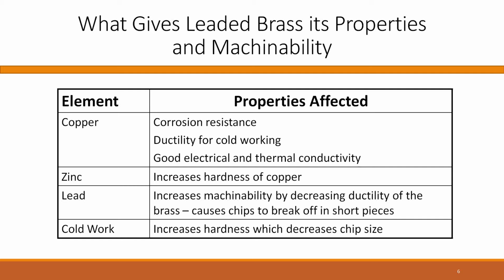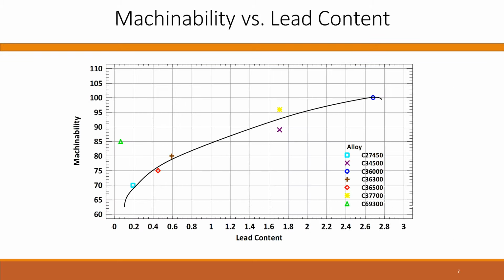Going on to the next slide, the old paradigm for machinability was the more lead you put into it, the more machinable it was. Well, because of regulations that have cropped up over the last 10 years or so, and I think Tom talks about that a little bit, you can't solve your machinability issues by just adding more lead anymore. This data here shows that as lead content goes up along the horizontal axis, your machinability goes up, as you can see, along the vertical axis.